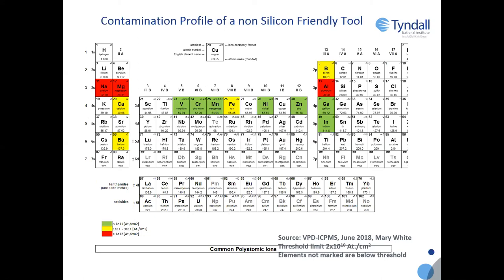Now, if we look at the contamination profile of a non-silicon-friendly tool, you can see it's a very, very different story. Here we're seeing sodium. Sodium is a real problem for a MOS device because it'll change your threshold voltage. It'll keep moving it around. It's not stable. We don't need sodium. Iron is showing up. Now, iron, while it's a dopant in indium phosphide, is a killer for a silicon device. We're seeing zinc, we're seeing nickel.